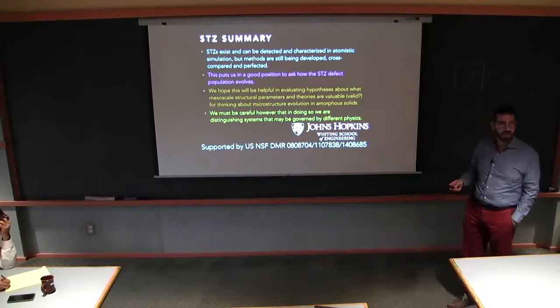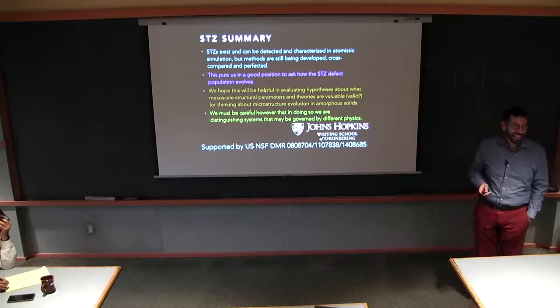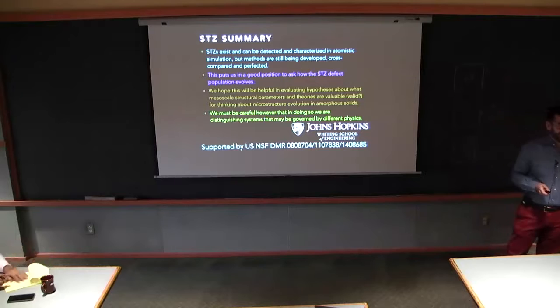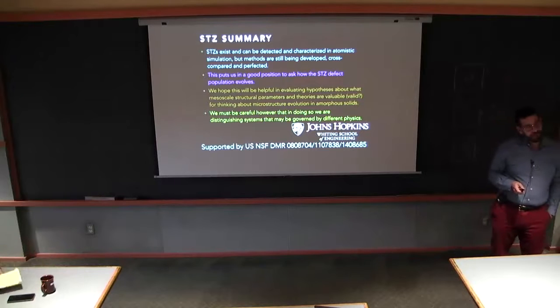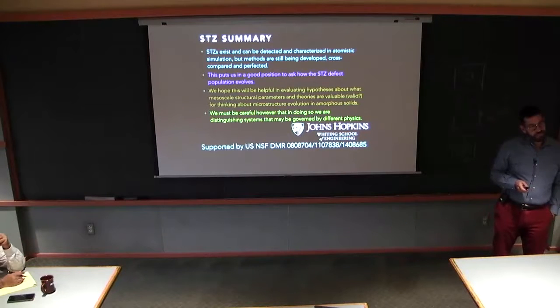Last question: when you have a shear band, the distribution of threshold yield stresses goes to a constant, no longer to zero. Is that right? Right, you reach a steady state inside the shear band.